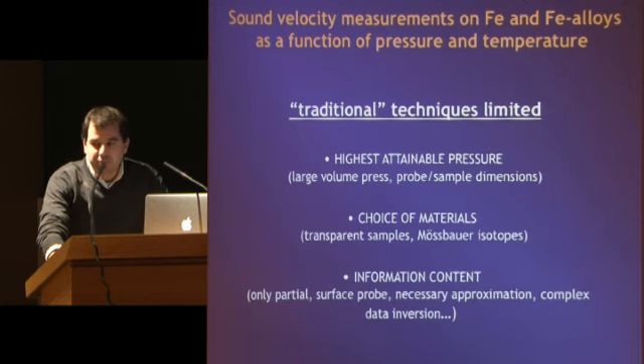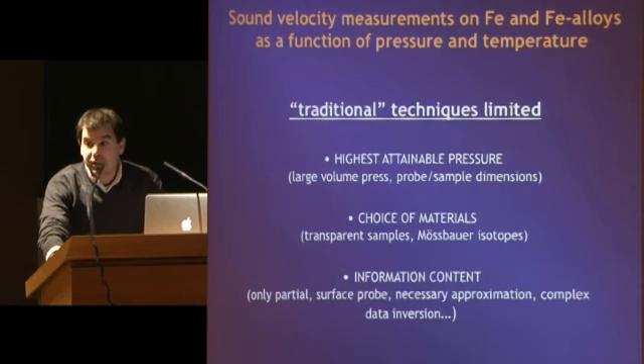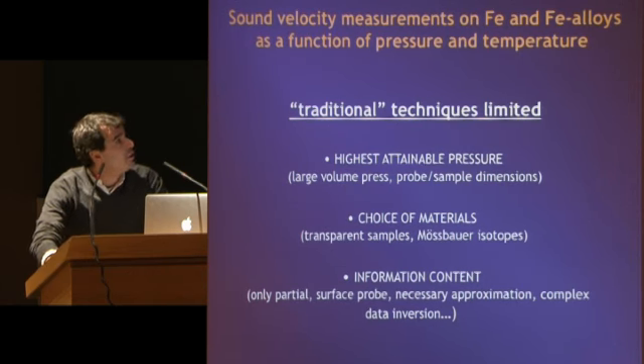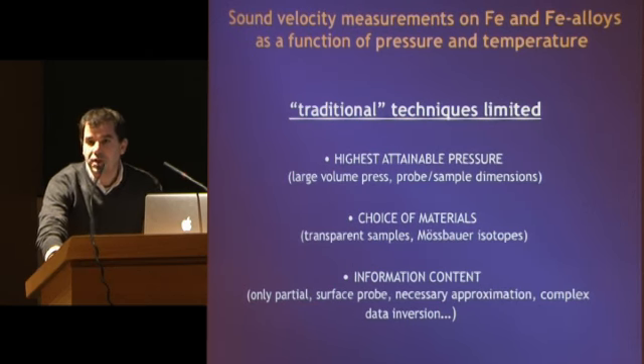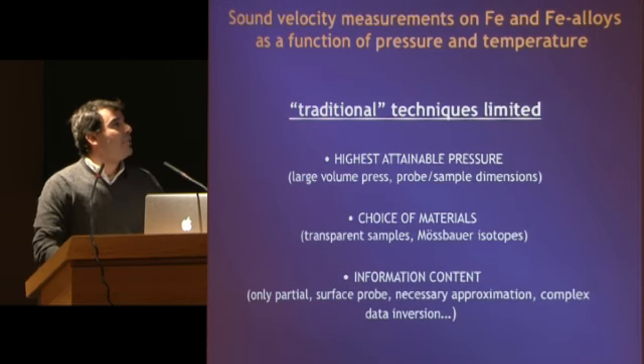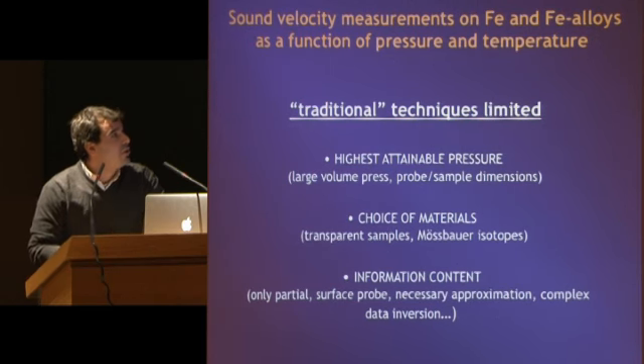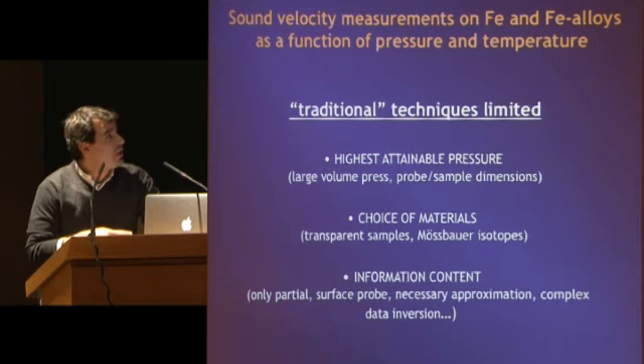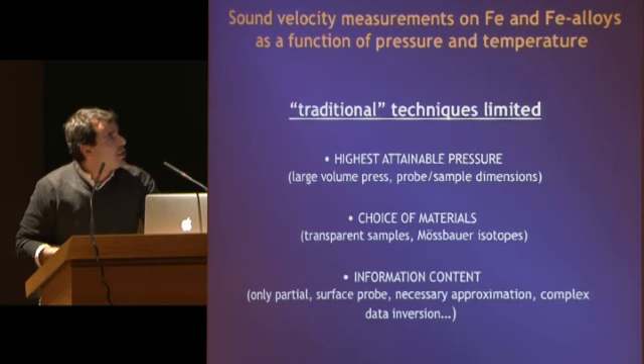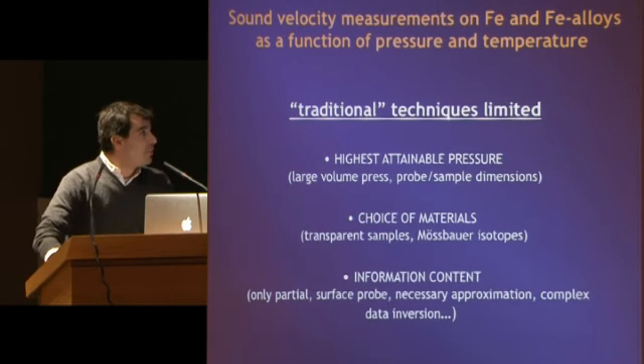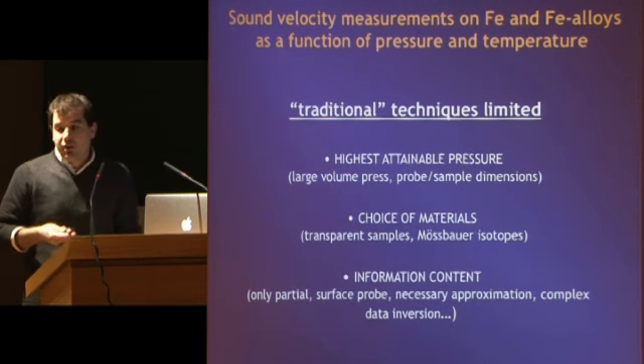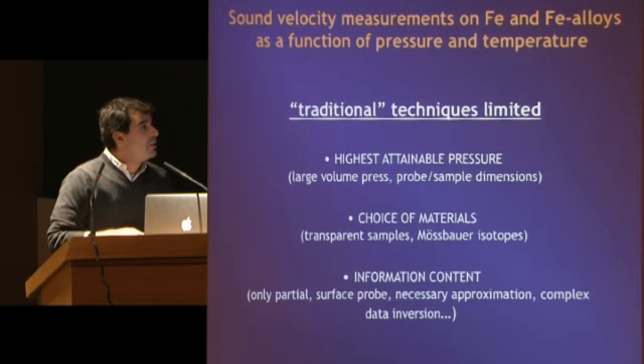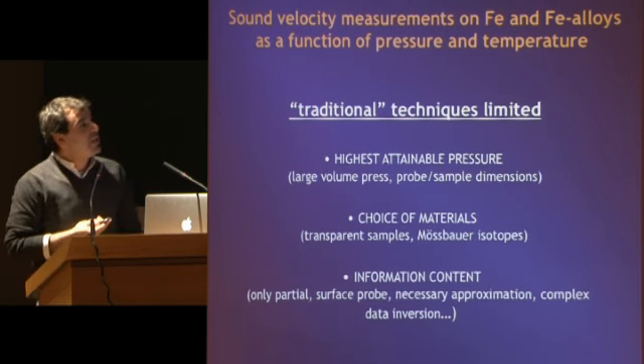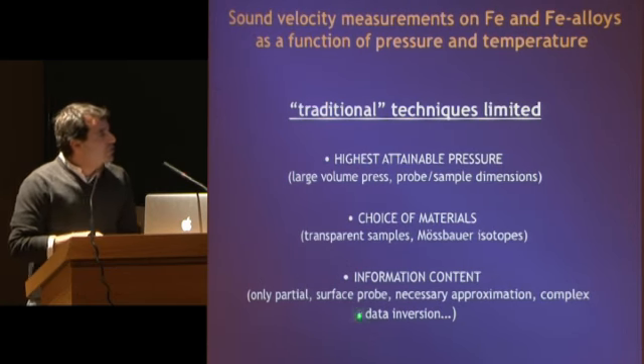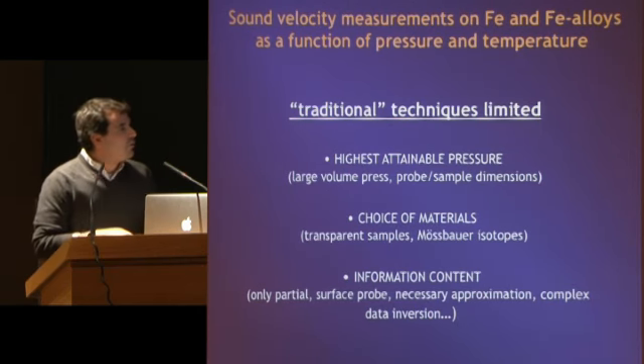However, performing elasticity measurements even at ambient condition is quite challenging, and traditional techniques such as ultrasonic investigation and Brillouin measurement all exhibit some limitation, be this on the highest attainable pressure. This is, for example, the case for inelastic neutron scattering measurement or ultrasonic measurement, where the probe or sample dimension implies the use of a large volume press, so there is a limit on the pressure we can reach. Another limitation comes from the choice of sample. Brillouin measurement and, in general, optical measurement are limited to transparent samples. In the case of metallic opaque alloys, it's particularly critical. Partial information, for example, can be derived from Raman spectroscopy or from surface probes.